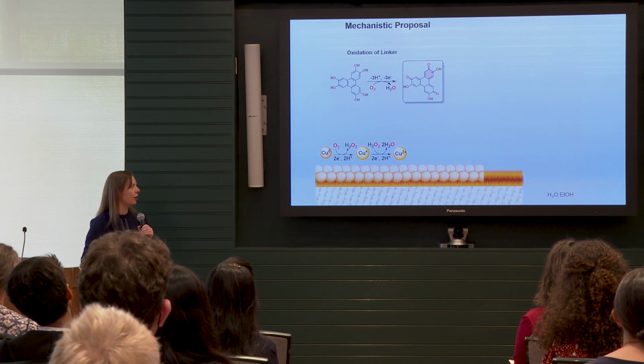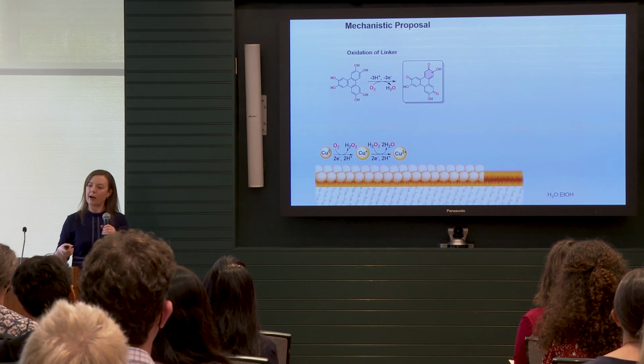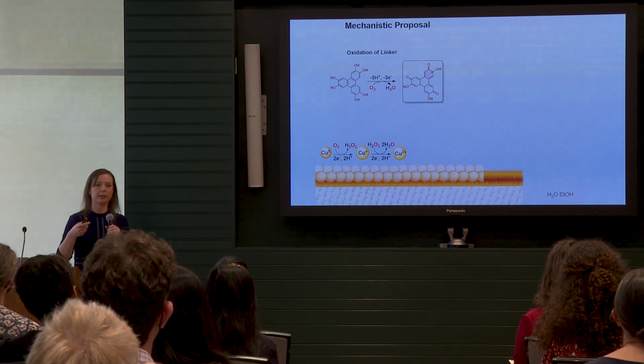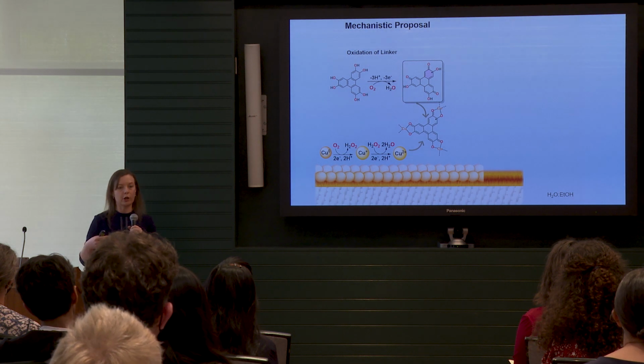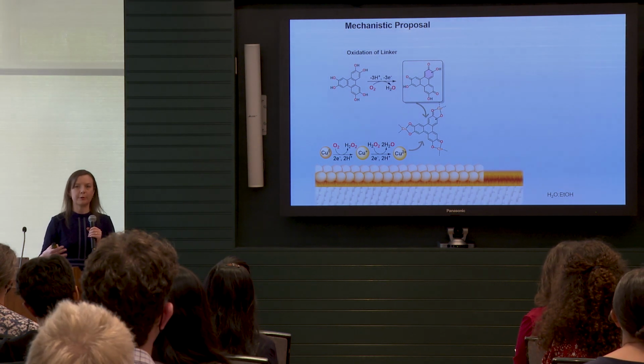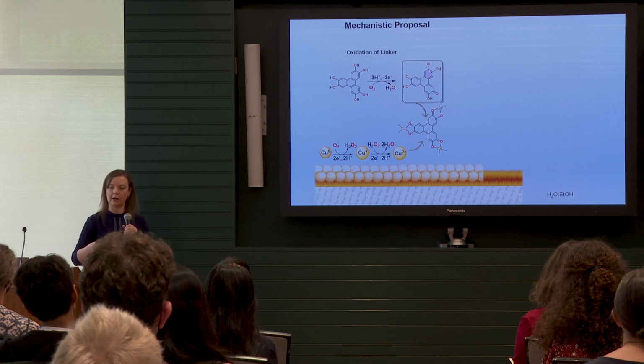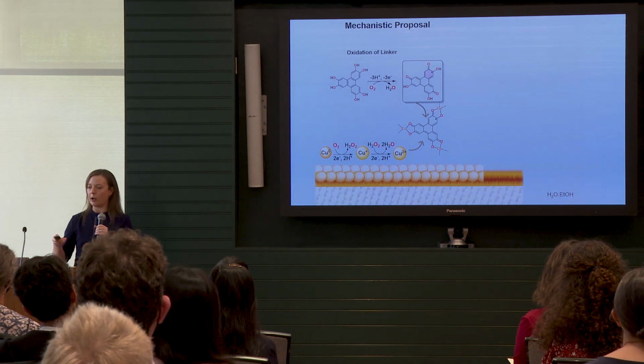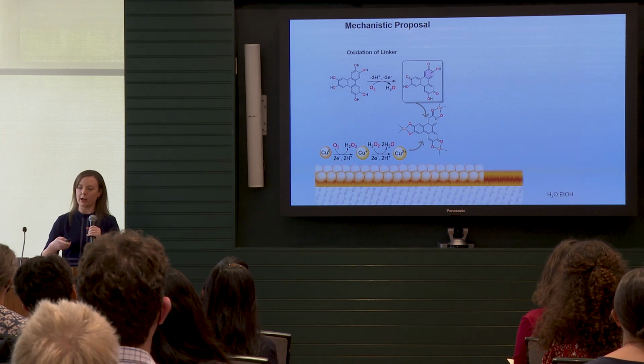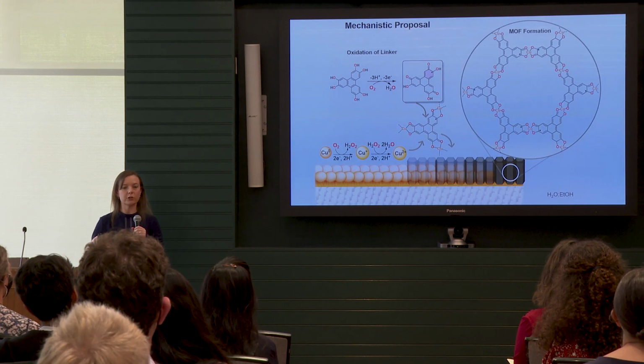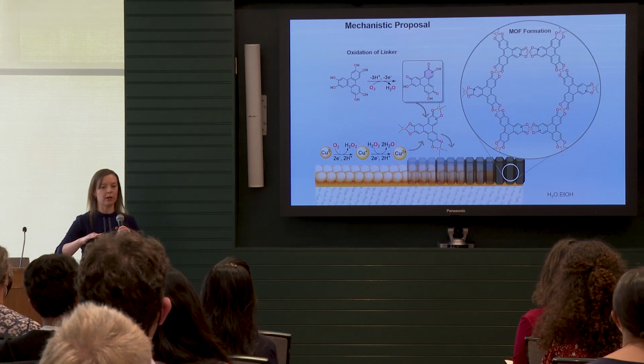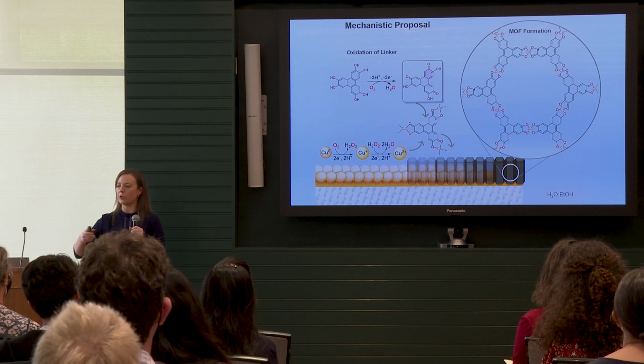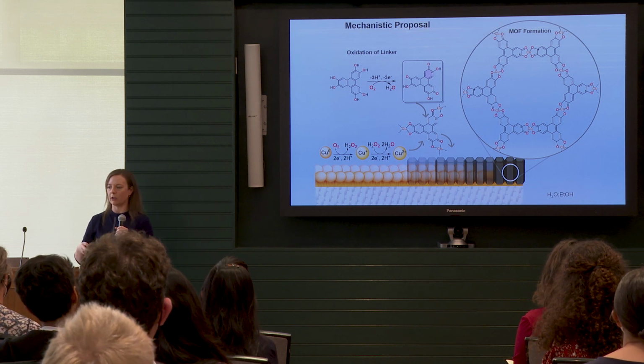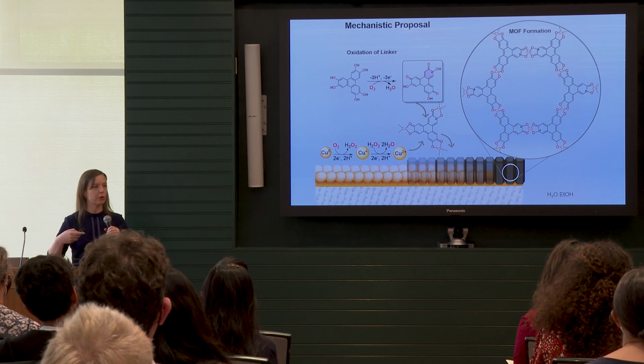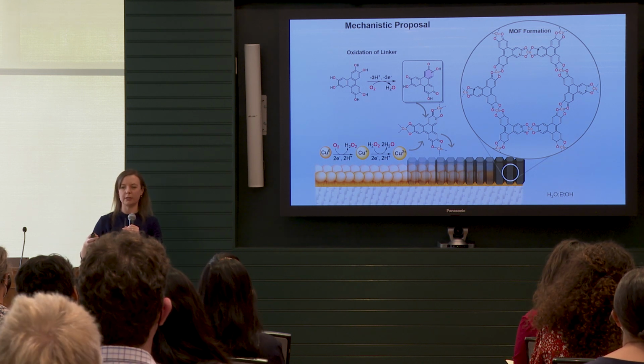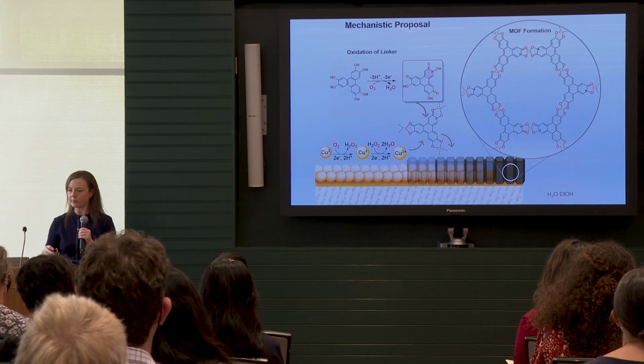In the presence of oxygen, we can oxidize copper. We also have a ligand, that organic portion of the framework that is redox active, that needs to undergo a redox event. Oxygen is absolutely critical to that entire process. If we take oxygen out, this does not work. And then once our partners are appropriately oxidized, a coordination event occurs, and because of the high effective concentration of copper metal at the surface of cotton, we're able to deposit the framework material onto the textile. And the kinetics works out beautifully to retain and maintain the patterning feasibility.